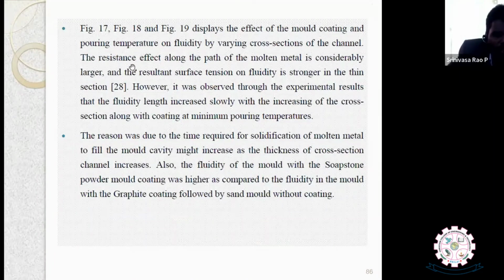It was observed through experiment that the fluidity length increases slowly with the increase of the cross section. The reason was that the time required for the solidification of the metal to fill the mold cavity might increase as the thickness of the cross section increases. So as the thickness of the cross section increases, the time required for the metal to solidify also increases. The fluidity of the soapstone powder mold was higher compared to the mold with graphite coating, followed by the sand mold without coating.